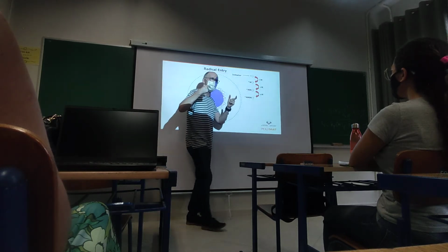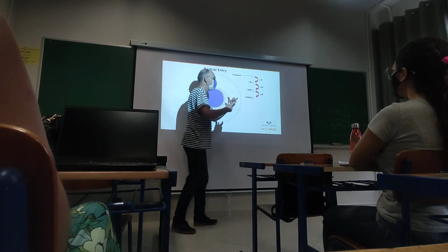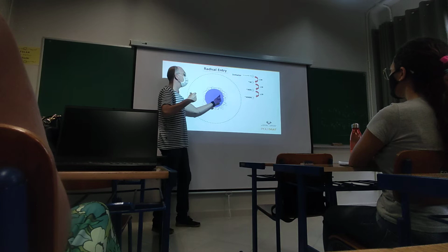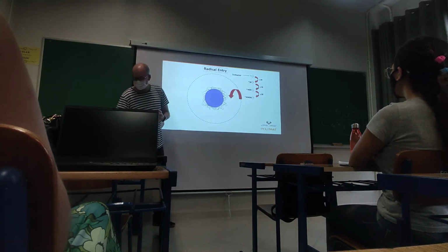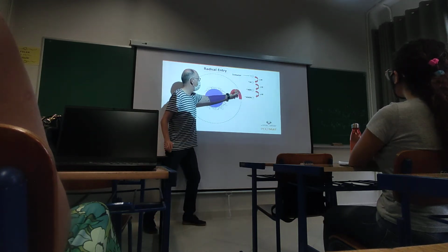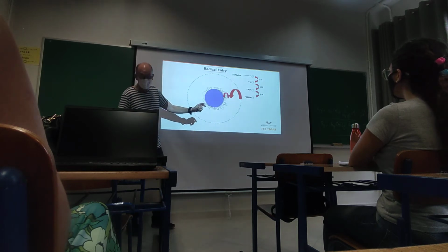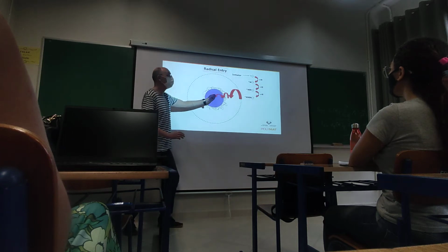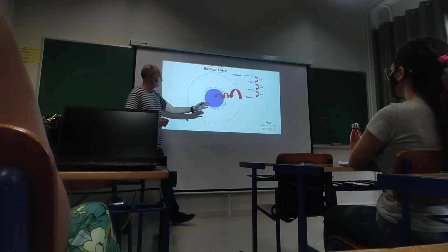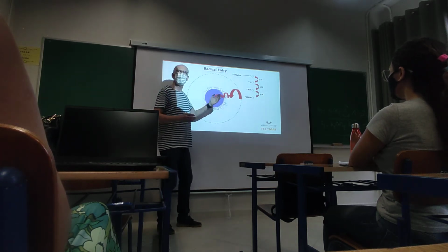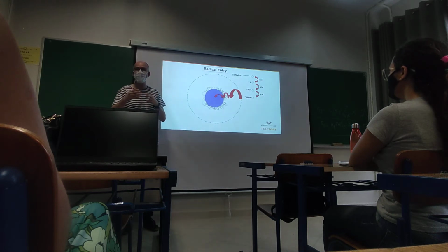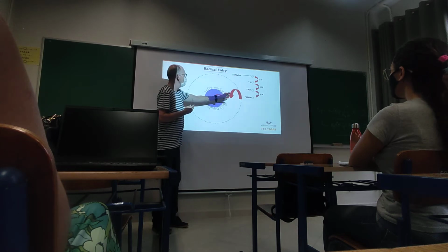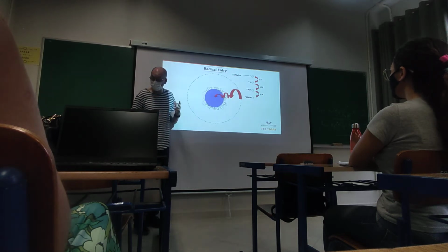The radical diffuses through this electrical double layer, so this aqueous phase, then in the Helmholtz layer, and then in the polymer particle. Each step is a resistance to diffusion, or a resistance to entering into the polymer particles. So these resistances can be modeled.